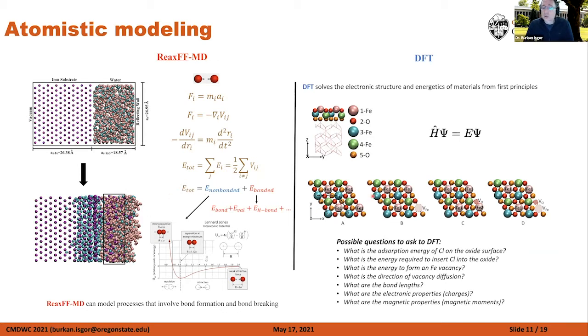You ask surgical questions to DFT, like what is the adsorption energy of chloride on the oxide surface? Or what is the energy required to insert chloride into an oxide? What is the energy to form an iron vacancy? Things like that, very surgical, very pointed questions. And DFT can answer those things using advanced first principles approaches. Now, all of these questions we covered in different papers.